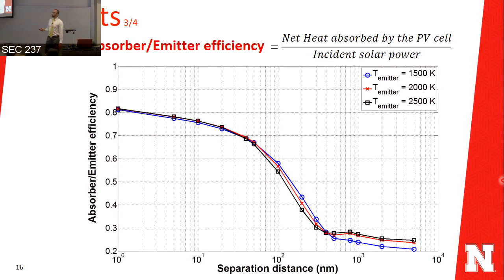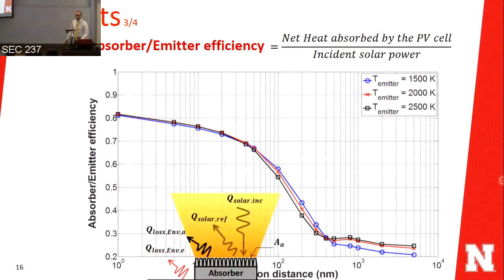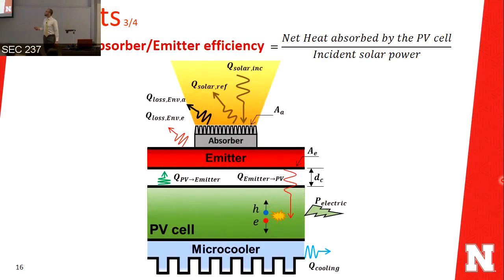The third piece of results is the absorber emitter efficiency, which is the ability of the emitter to transfer the incident solar power to the photovoltaic cell. The lower the separation distance, the higher the absorber emitter efficiency, and this is one of the main findings of our research. By just decreasing separation distance, you can increase the energy absorbed by the system. And why does this happen? You have the losses from the absorber emitter. They are just a function of the temperature of the emitter. As long as the emitter temperature is constant, the losses are the same. So once you decrease separation distance, you increase the solar incident because you are increasing the concentration, while the losses are constant. So you should expect decreasing separation distance will increase absorber emitter efficiency.